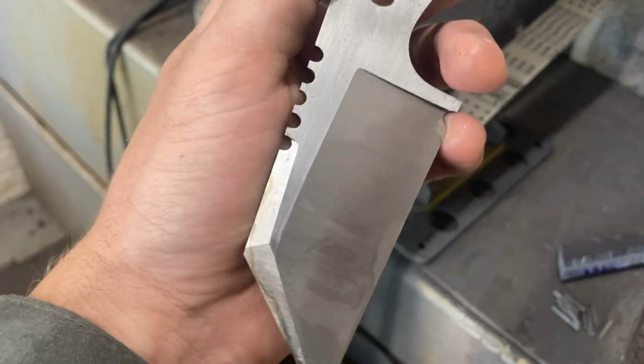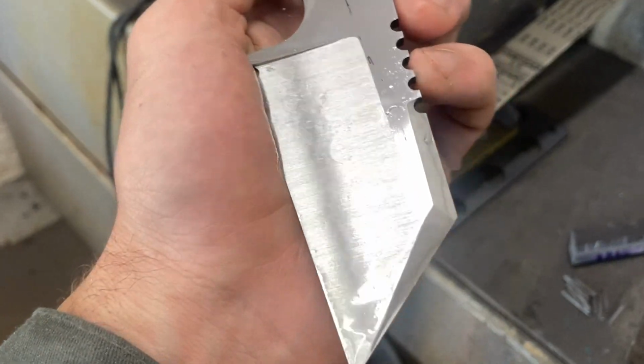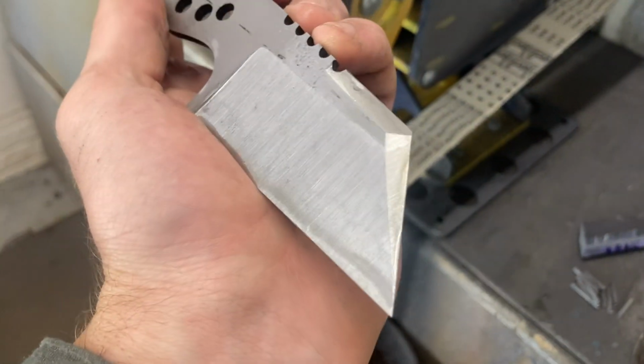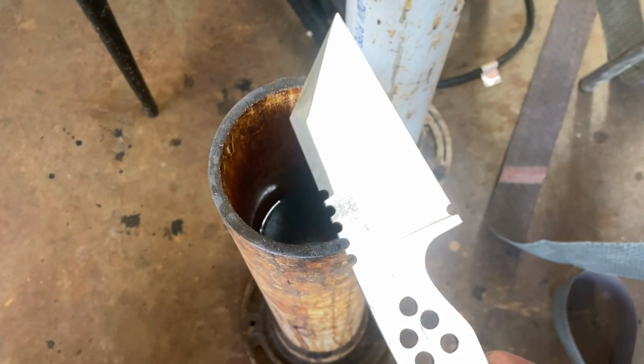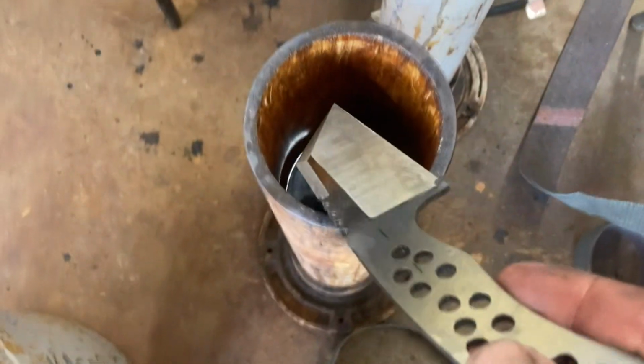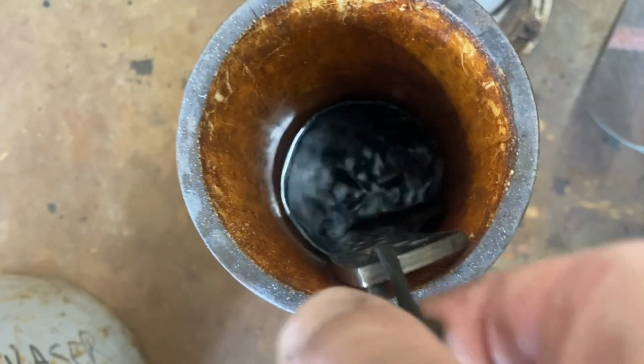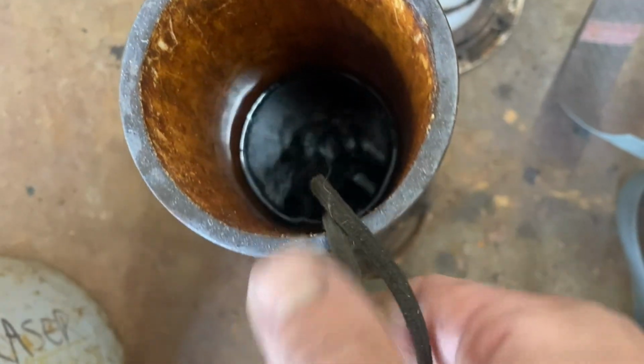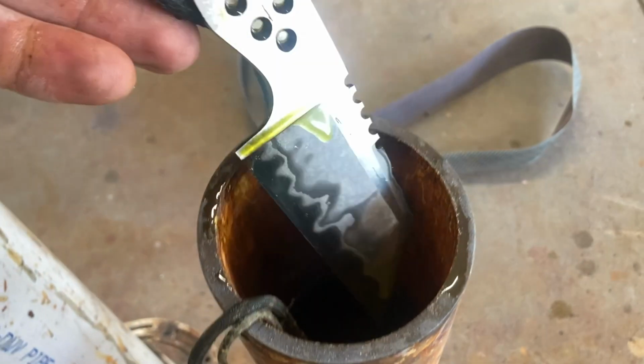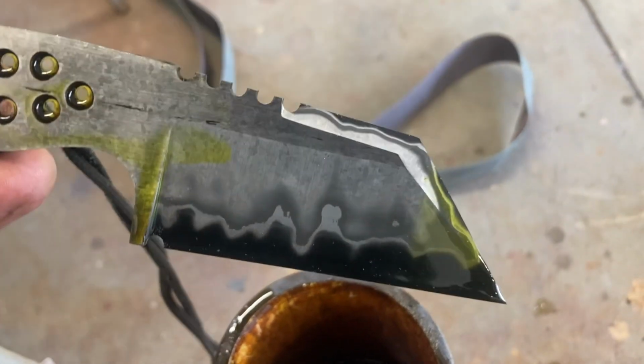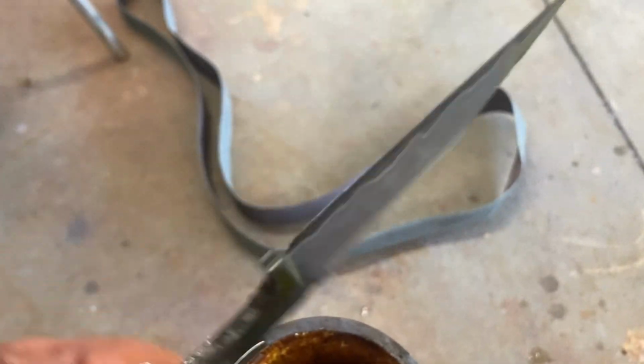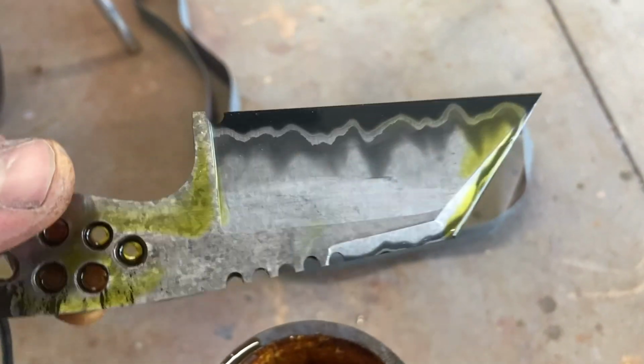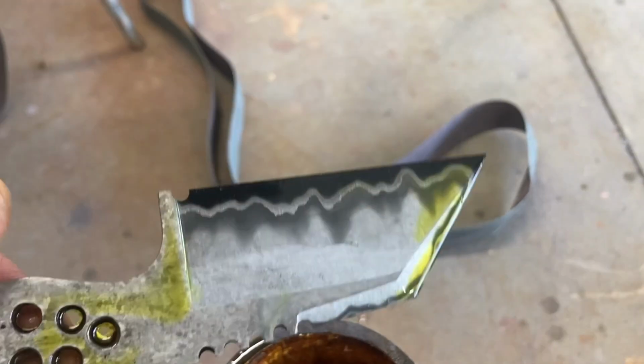Here you can see the final polish of the bevels before etching. I always degrease before doing the etching process as well. And now it's time to reveal the pattern in the steel, which I do by first etching in ferric chloride acid for around 15 to 20 minutes. I have it cut down to a 50-50 mixture with water, and that enables me to see the nice dark pattern.